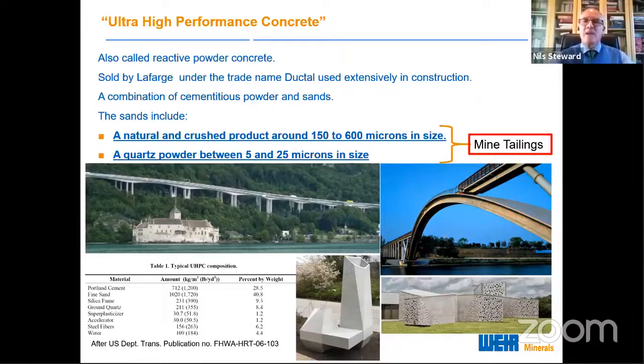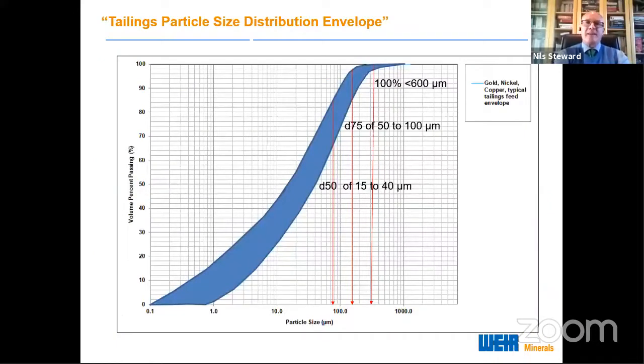So where are we with our typical tailings particle size distribution envelopes? Just keep this in mind, that we're looking at 100% below 600 microns. We're looking at D50s of 50 to 100 microns. Sorry, D75s of 50 to 100 microns and D50s of 15 to 40 microns. So it's particularly fine. What I've done is put together an envelope here of materials that we've worked with, from the gold, nickel, and copper typical tailings, and their particle size distributions. And we'll be only investigating these size distributions. We have done work with iron ores, and we'll talk about that later.